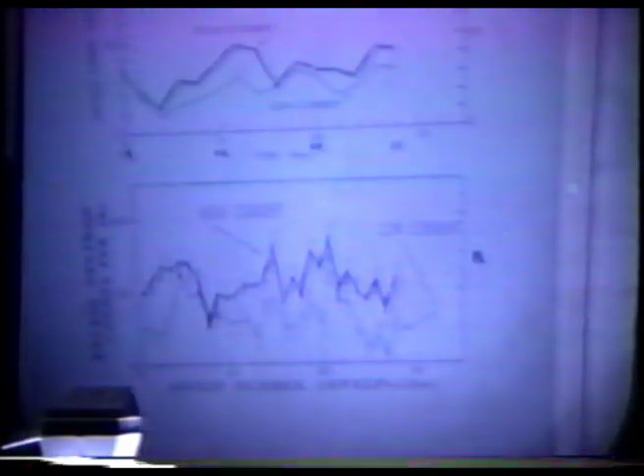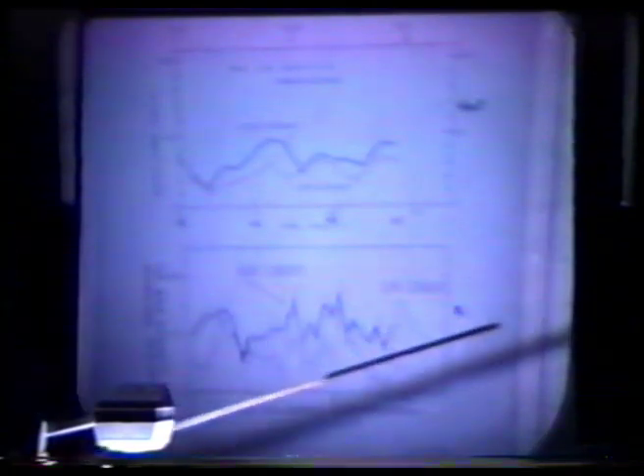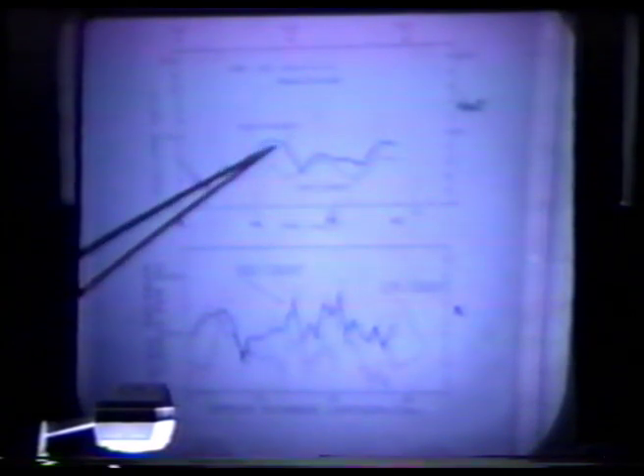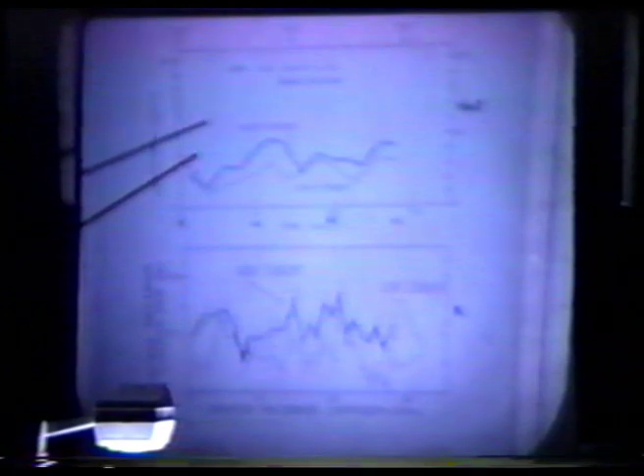Using that method, he has found, well, I think there's still some questions with his calorimetry. His calorimetry is not the best, but if his large effects are true, I think he can get by with the poor calorimetry. So he's measuring excess power here, low current and high current. He's up here almost over 40 watts of excess power. Now, if you're getting that kind of excess power, you can get by with poor calorimetry, if that is real. But he gets more excess heat with the high current than he does with the low current.